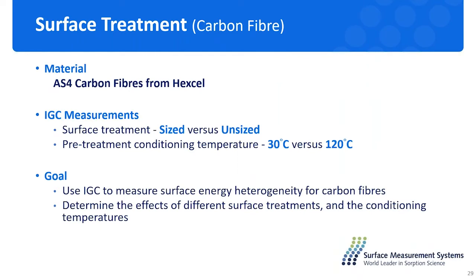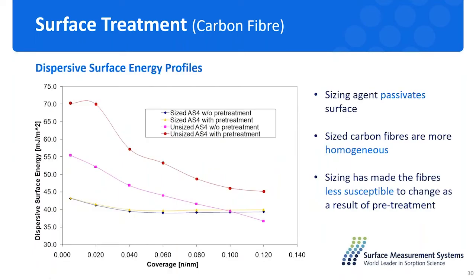And the next case study is related to carbon fiber. Carbon fiber is quite useful in the medical industry nowadays because of its light weight and also its high strength. And we can always change the nature of the carbon fiber by a sizing procedure, and different pre-treatment conditions will also have an effect on the nature of the material. So we want to study the sizing effect and also the preconditioning temperature effect on the material with the IGC technique. So we measured 4 different kinds of carbon fibers, sized and unsized carbon fiber at 30-degree preconditioning and also 120-degree preconditioning. And here's the distribution of the surface energy.